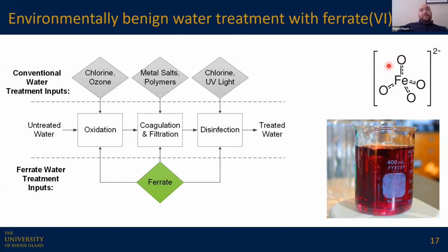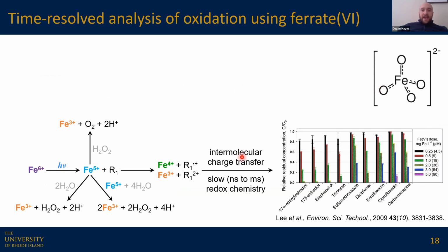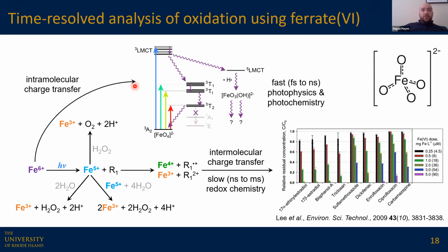We're interested because it has potentially interesting photophysics, and also it's a very rare example of such a hypervalent transition metal complex. It's the only known shelf-stable iron 6 compound, and so we were surprised to find that there was essentially no literature on its time-resolved dynamics, and so we set out to fix that. So what had been done in the past were these studies of the efficiency of intermolecular charge transfer following photoexcitation of ferrate in degrading these common pharmaceutical contaminants in drinking water supplies. But these are all steady state measurements of this slow intermolecular redox chemistry. We wanted to look at the intramolecular charge transfer following UV excitation into this triplet LMCT from the ground state triplet state and see what happens after that.